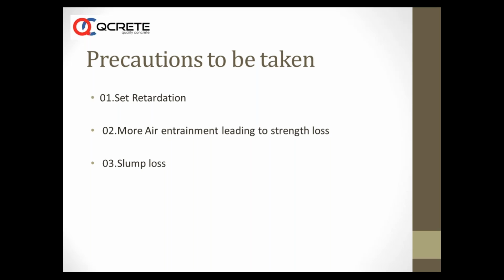So we waited for almost. We started taking extra cubes from the same concrete which was cast, because of the severe retardation, and slowly strength gained. We tested up to 3 months. The concrete gained strength eventually. So these were some of the bad effects of retardation caused by lignosulfonate based admixtures, which could not operate in higher cement contents and could not operate when changes were taking place in the cement compositions.